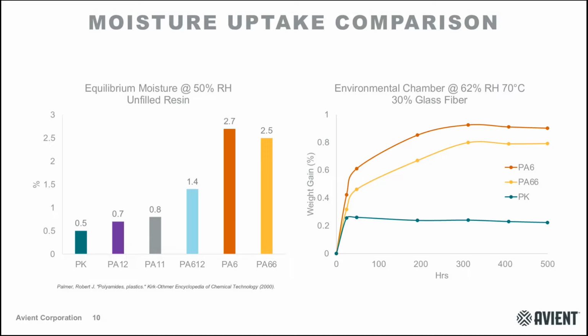There's also going to be a noticeable difference in the moisture uptake behavior of polyketone when you add in typical reinforcements and additives, in this case, 30 weight% short glass fiber. And we're showing this as a rapid moisture aging study on the graph on the right. In this case, we're taking samples and aging them at 62% relative humidity, 70 degrees Celsius, over a period of 500 hours. Again, a higher data point here indicates more moisture being taken up.